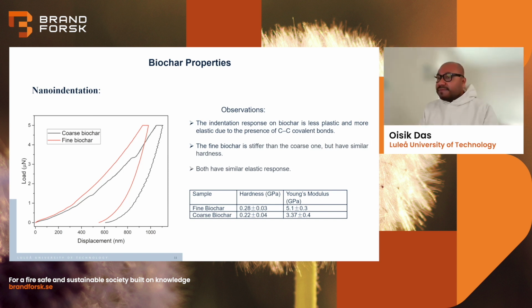We also see that the fine biochar is more stiff than the coarse biochar, but both of them have similar hardness and both have similar elastic response. But the stiffness or the Young's modulus of the fine biochar is definitely higher, which is around 5 gigapascal, and for the coarse biochar is about 3.3 gigapascal. But the hardness of both the biochars is quite similar at 0.2 gigapascals.